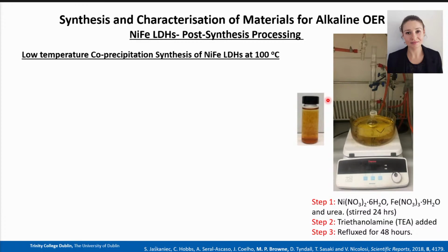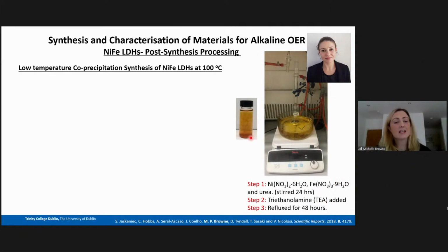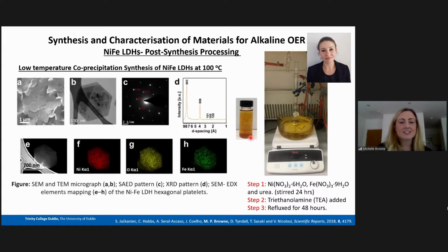So essentially what you will make here is two different intermediate catalysts. You will make a nickel TEA based catalyst, and then you will also have some iron oxyhydroxide material too, which is the brown color, which you can see here. Then this solution is added into a round bottom flask and is refluxed for 48 hours. And essentially what we get at the end, or what Sonia gets at the end, is very nice nickel-iron LDHs.